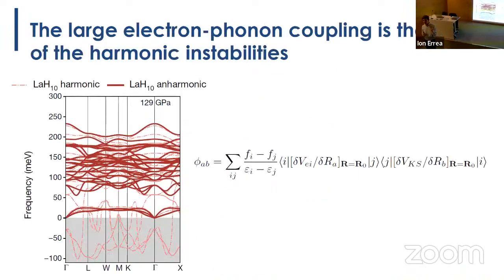So one remark here that I think is important to understand a bit: why does this system have such a huge harmonic phonon instability? It is because of the huge electron-phonon coupling in this system. And this is known: the electron-phonon coupling is a destabilizing force in a material. So if you have a large electron-phonon coupling, the system wants to distort to reduce the energy. And this is what happens.